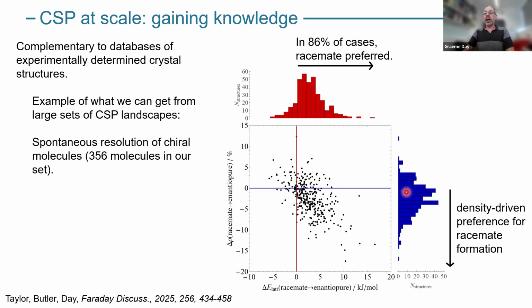When you have symmetry operators in your crystal structure, like inversion centers or glide planes, those can aid in fitting molecules together into high density structures. And those symmetry operators are only possible if you have both handednesses of your molecule in the structure. So we can understand the scale of how much of this is driven by density by having this really large set of predicted landscapes of structures.